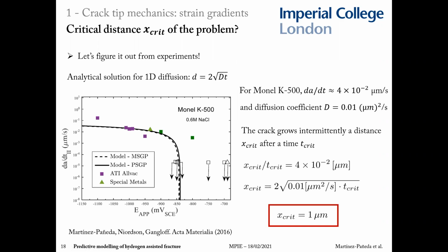So for example, in the case of this nickel superalloy, we can see the stage 2 crack growth. The stage 2 crack growth speed, in these 3 replicate experiments at a potential of minus 1,000, gives us a value of 0.04 microns per second. And since we know the material diffusion coefficient, we can measure that independently.